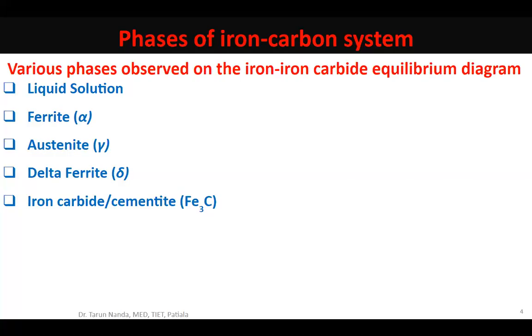Another thing about cementite, students, is that cementite is not a true equilibrium phase. At whatsoever temperature it exists, low or intermediate or high, it exists as a metastable phase. Metastable phase, as we have already discussed, means it is not an unstable phase that over an observable period of time gets converted into some other phase, nor is it an equilibrium phase. Why isn't it an equilibrium phase if it does not break?